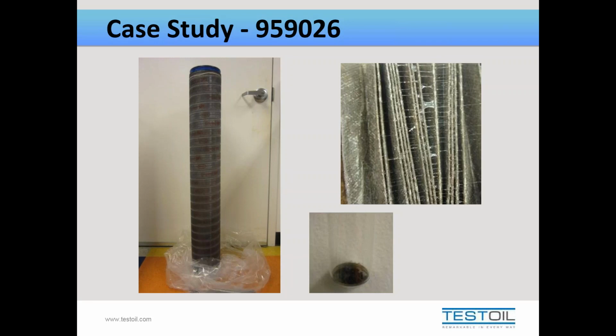So while going through our washing process of the filter media, we found degradation products of the fuel. We found carboxylic acid. But then we also found quite a bit of an EVA additive degradation products, which are materials such as olefins and carboxylates. So really, the sticky resin we found was a combination of carboxylic acid, which resulted from degradation of the fuel itself, water, and EVA, the fuel additive degradation product. And for that to come out, it really suggested that this system had been improperly blended with the additive. And the improperly blended additive most likely resulted in a hydrolysis reaction with the water to cause this really, really sticky mess that the filters were catching.